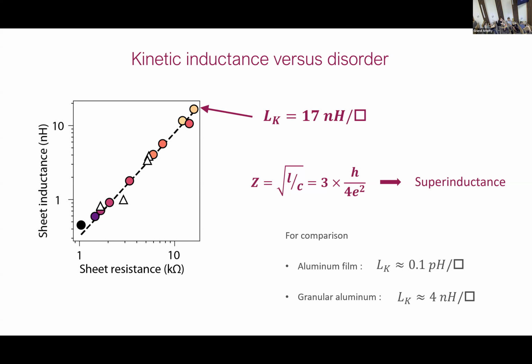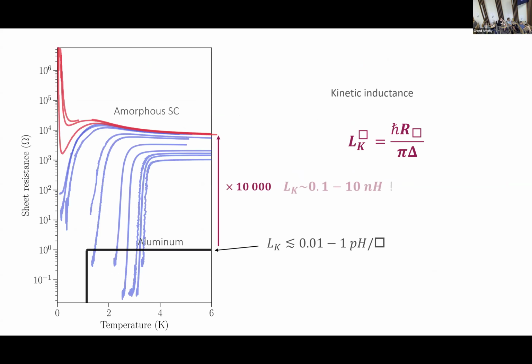It's a bad disorder limit, which is not described by BCS anymore, Anton would say. Certainly. But in any case, if you measure the response, in a sense we don't care about that formula from an experimental point of view, right? For application, you just get something which is some impedance with some frequency dependence. If it looks like an inductance, then it is that inductance. Exactly. But square resistance is not anymore the right scaling. No, that I agree. But in the sense of application, the number is the layer scale that you care about, whether it follows that.